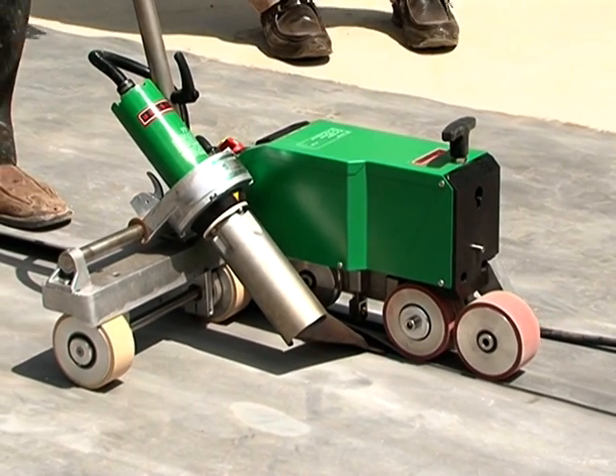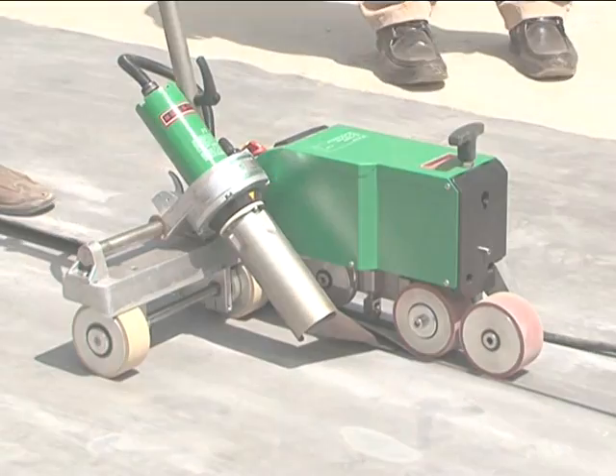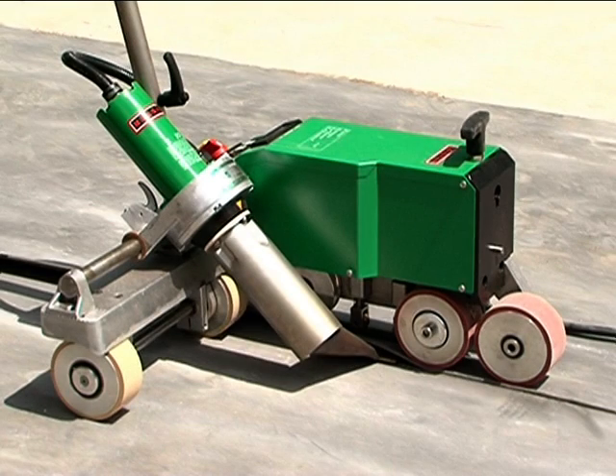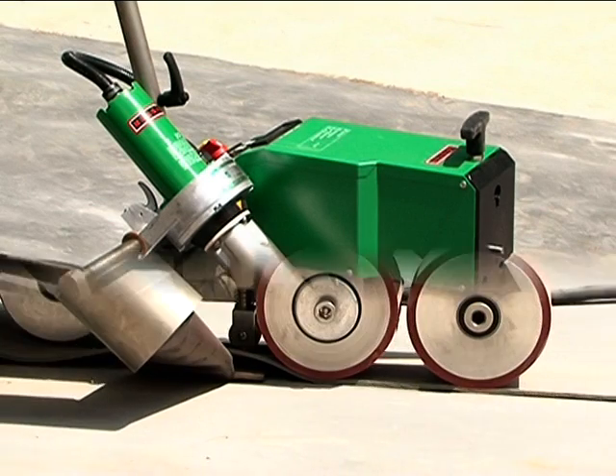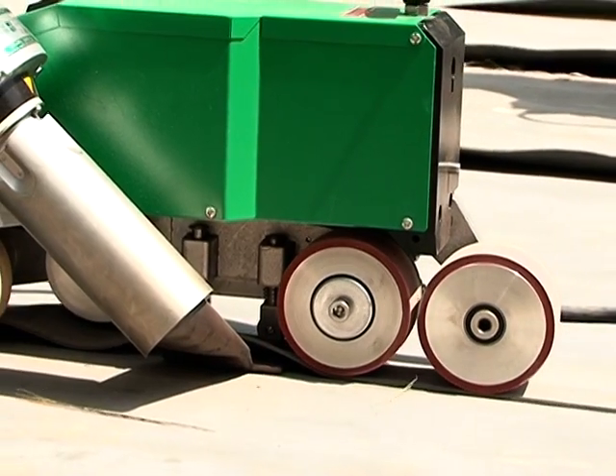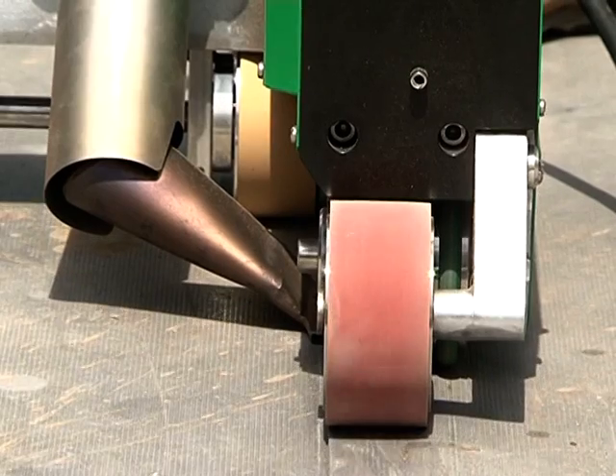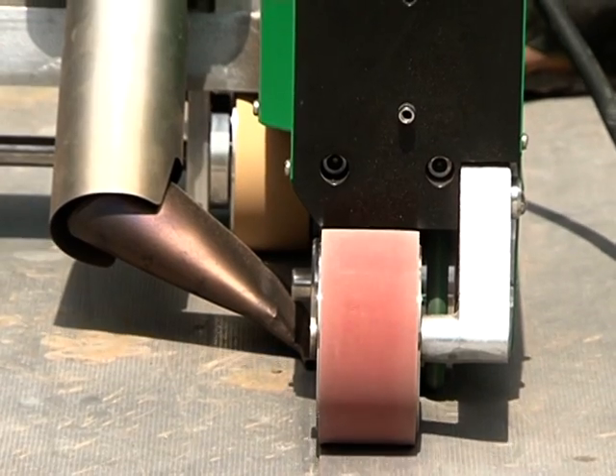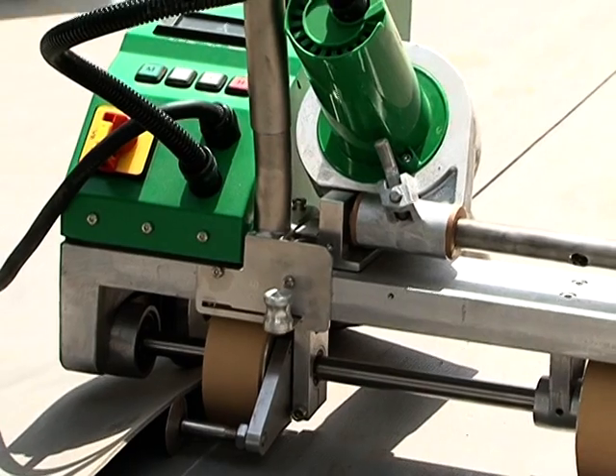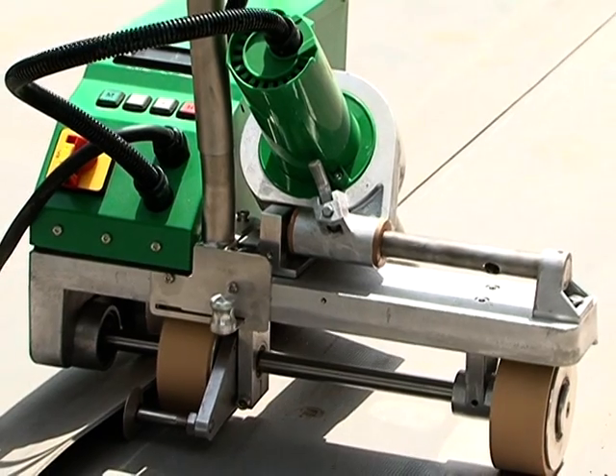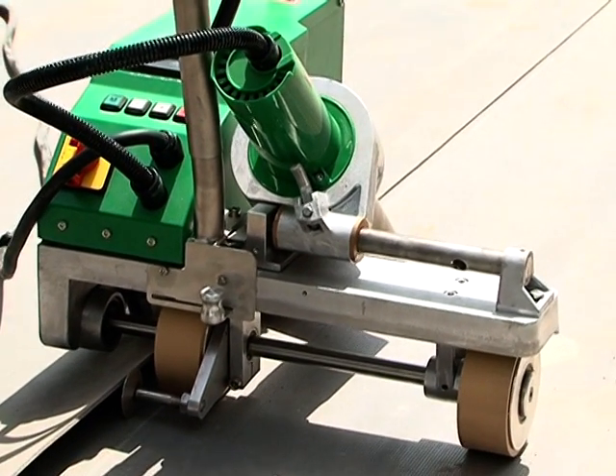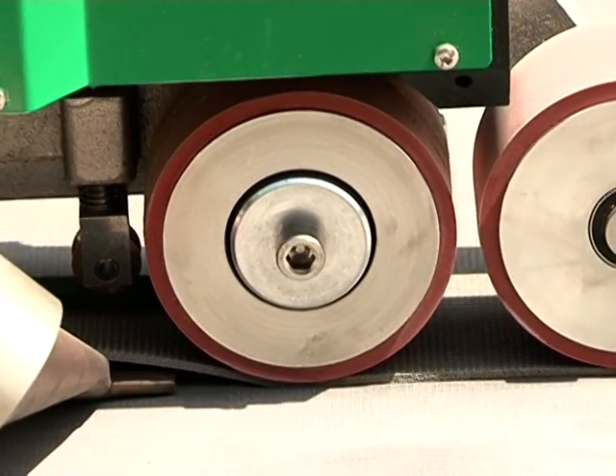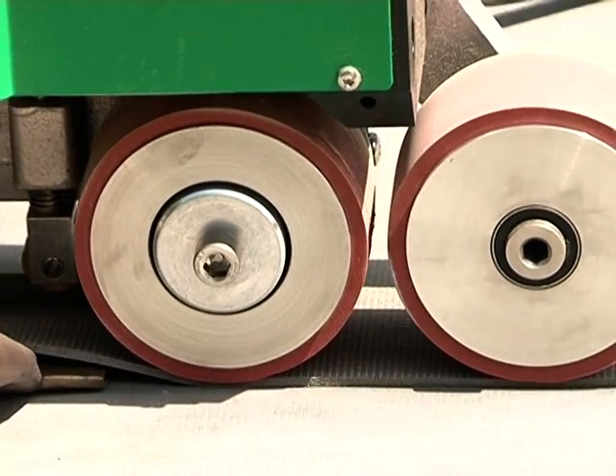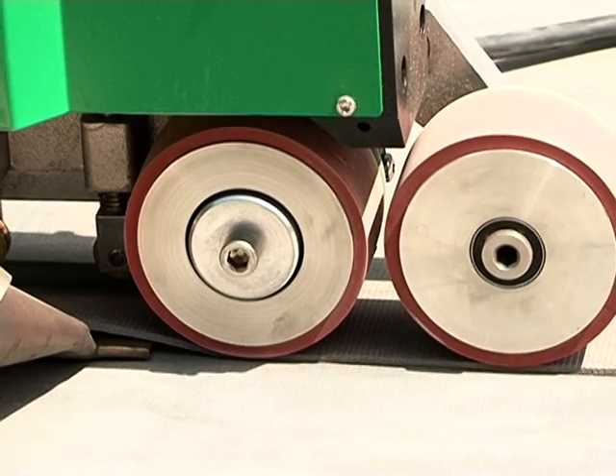Fifth application stage, heat sealing. The overlap of 50 mm between the two membranes is heat sealed with Leister Varimat hot air automatic sealing machine. The mouth of the heating nozzle is lowered down and guided to position itself exactly between the two membrane layers which need to be sealed. The temperature of the machine is set at 360 degrees. The airflow is constantly maintained at 10 liters per minute and the wheel rotation speed is set at 3 meters per minute.